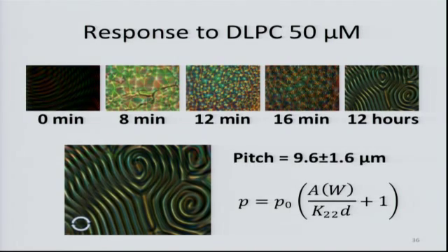And that has to do with the observed pitch when we have a fingerprint texture. It depends on the intrinsic pitch when we have a planar alignment, but then it scales with some coefficient here that I don't really know the form of yet, but it depends on the anchoring strength, and also on the elastic properties of the cholesteric liquid crystal, and on the thickness of the film. That's how much I know now.